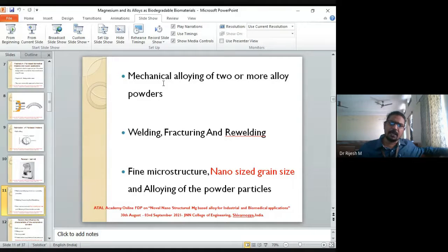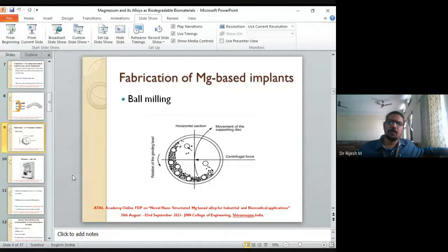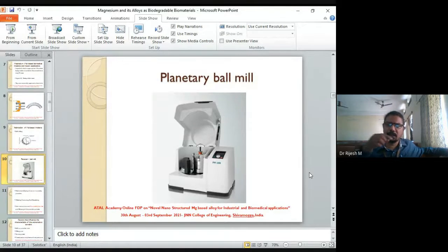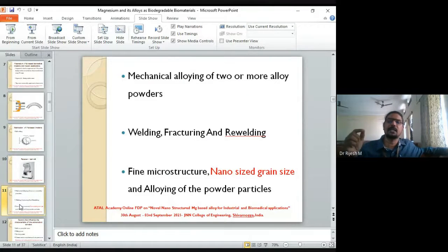Now, how do you know that mechanical alloying has taken place? You sample some of the powders from this drum and go for an XRD analysis. You get peaks corresponding to the planes that exist in that particular alloy. So if you are getting a peak or intensity for a plane corresponding to a certain alloy, that alloy has been formed. If not, it has not been formed. You will get individual peaks for individual elements.